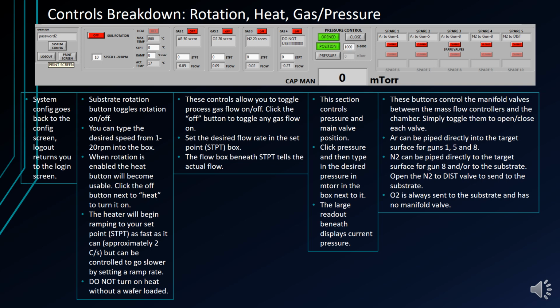The last section controls valves which route gas from the mass flow controllers to different entry points in the chamber. Notice that the first three say argon to guns 1, 5, and 8. These valves inject gas into the chamber through the gas injection rings for those guns. It's recommended that you flow argon into these guns whenever you are using them, especially when flowing oxygen or nitrogen to form compounds. If you are using guns without a valve to them, it's recommended that you flow gas in through gun 8, as it is centrally located and equidistant from all the other guns.